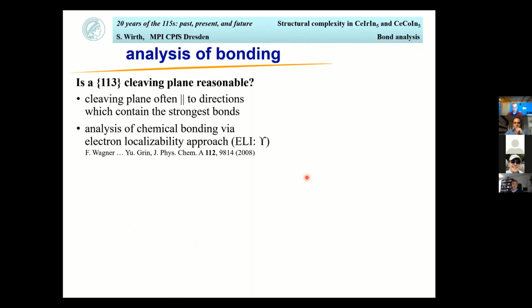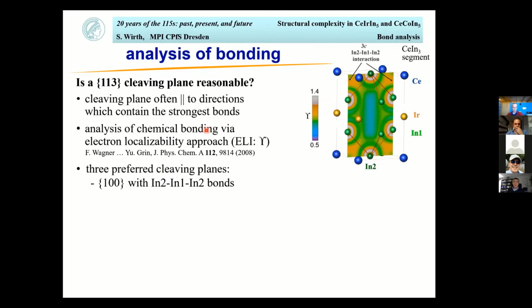Now, of course, the question is, this is a strange plane, 113. So is this actually reasonable? And that's again where Yuri Grin came into play. He did an analysis of the chemical bonding via the electron localizability approach. And the idea is that the cleaving probably takes place along a plane that keeps the strongest bonds in place. So with this bonding analysis, we should be seeing where a cleaving might happen. So this is what he got.